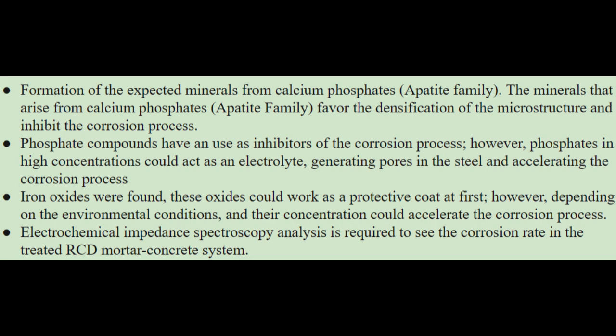Iron oxides were found. These oxides could work as a protective coat at first. However, depending on the environmental conditions and their concentration, they could accelerate the corrosion process. Electrochemical impedance spectroscopy analysis is required to see the corrosion rate in the treated RCD mortar-concrete system.